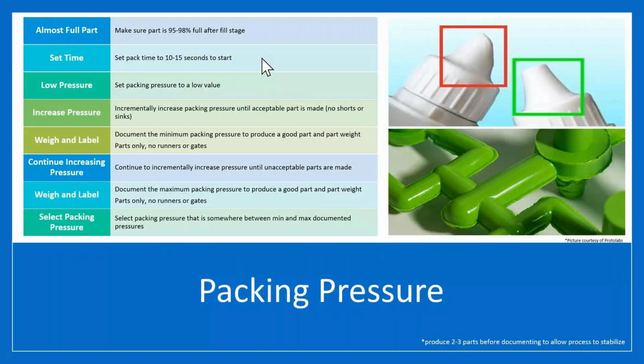So from there, we need to figure out how much pressure to pack with, and then we need to figure out how long to pack for so that we can seal off. How hard we pack, how much pressure we use, is directly related to sinks, voids, and then flash. So we want to establish our 95 to 98% full. We're going to set our packing time high, typically around 10 to 15 seconds. That should give us some approximation of a gate freeze. We're going to start with a low pressure, and we're going to mold a part with a low packing pressure for 10 to 15 seconds. That should produce us a short shot.